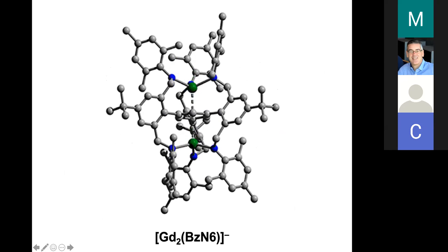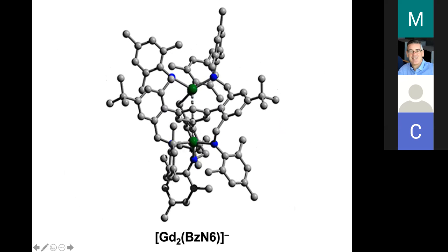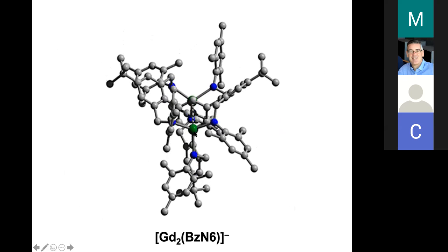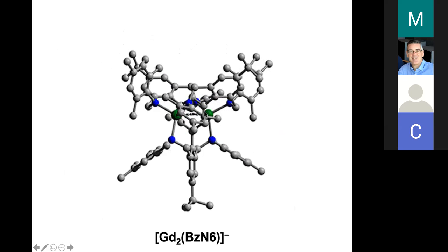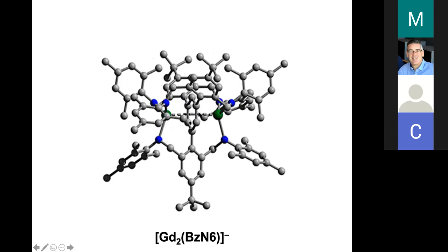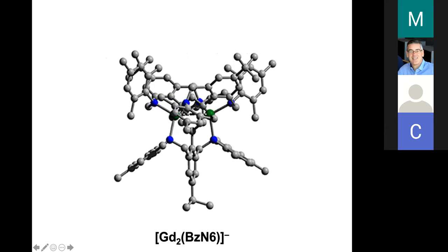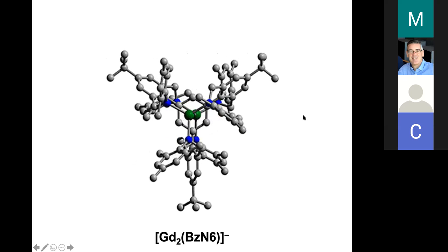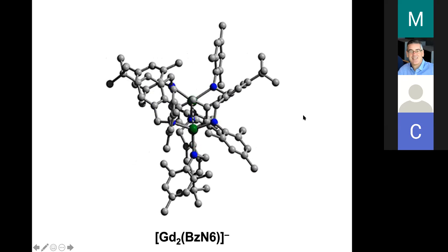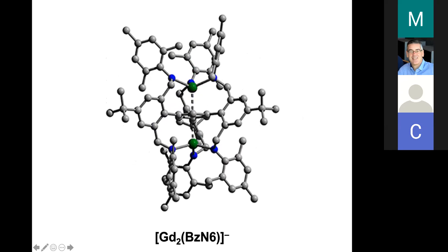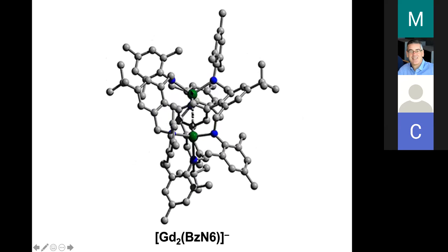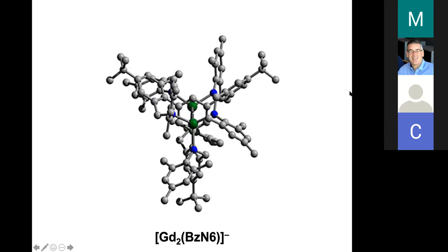And so you have this sort of tetrahedral coordination at the lanthanide on each side, but this ligand is forcing those lanthanides to come in close to that benzene ring. This is what's called an inverse sandwich complex. So normal sandwich complex, you have two flat aromatic ligands with a metal in the middle. Here you've got the flat aromatic in the middle and the metals on the outside.